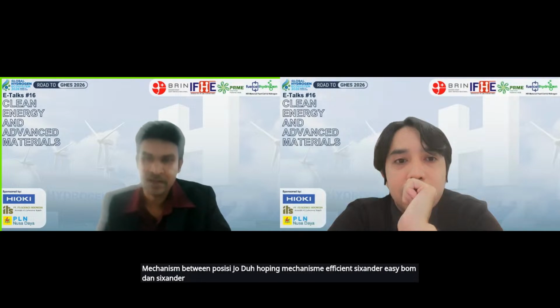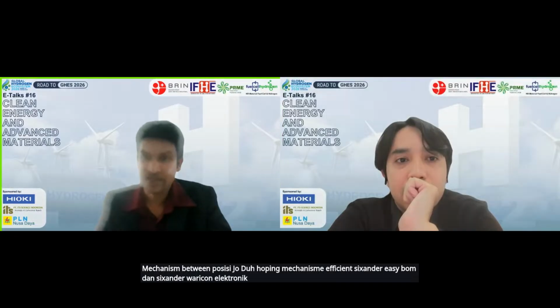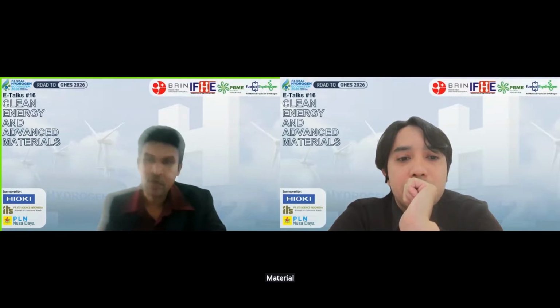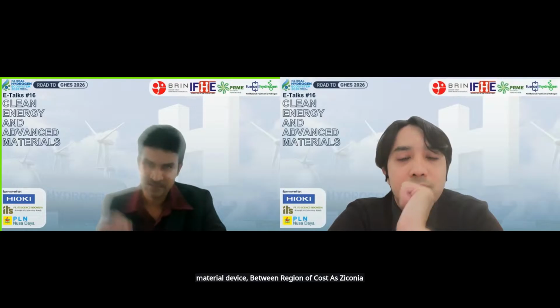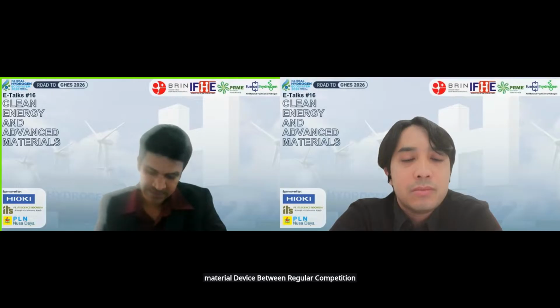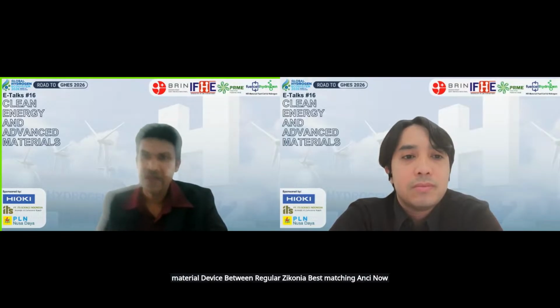If you go more than 600, there will be some issues, what we call the electronic conduction issue, and there are many issues. So in the selection of material, of course, zirconia-based material is the best, cheap, and very, very stable compared to ceria-based material. That is why people use zirconia-based material. Until now, this material is still in demand for the fuel cell and electrolyzer industries for solid oxide.